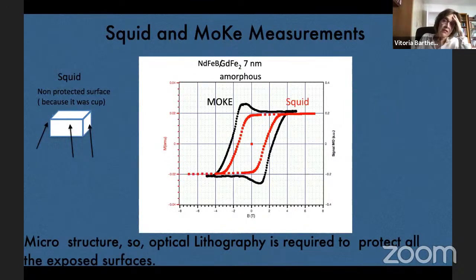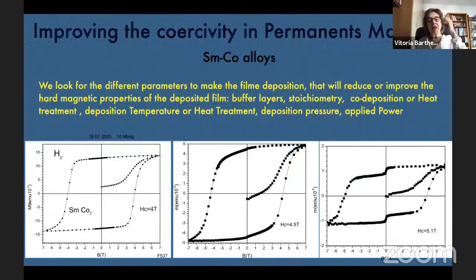At the same time, with these hard magnets, we are trying samarium cobalt alloys, and we are trying to optimize the magnetic properties, in fact focusing on coercivity. So we are changing the stoichiometry of the codeposition, the temperature of the codeposition, the buffer layer, the deposition pressures, or the power, that is, the rate of deposition. And at the end, you have a good answer.